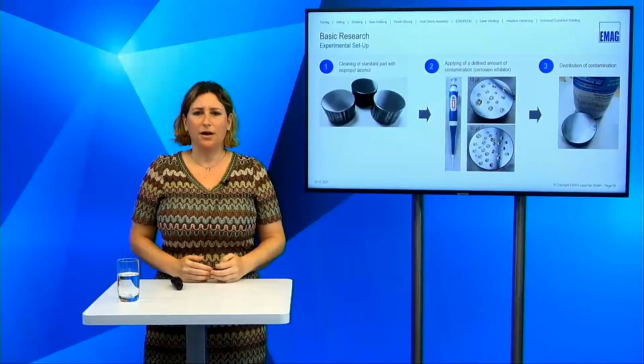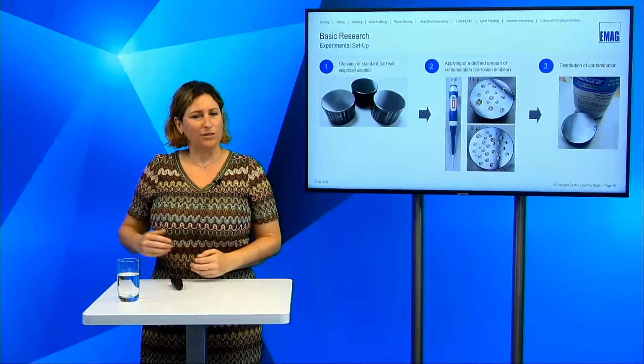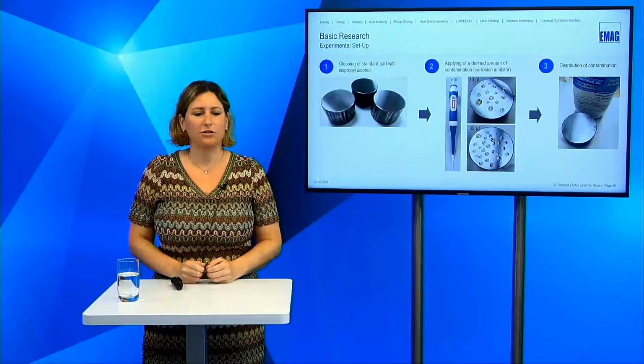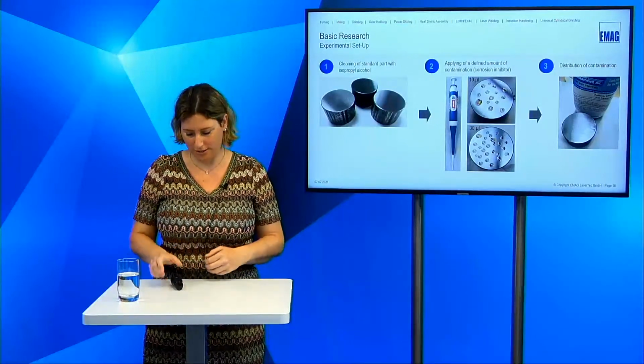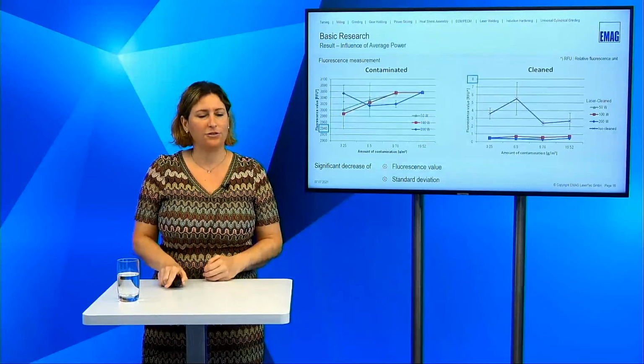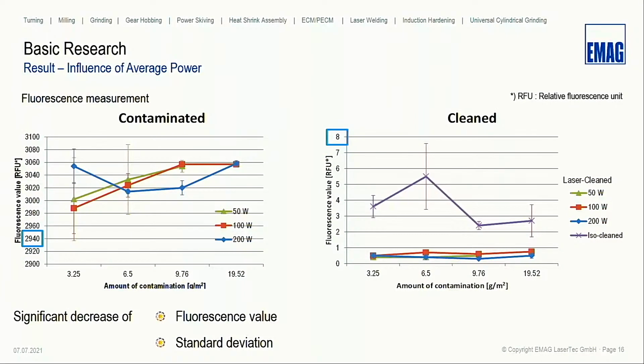How this looks like when you laser clean, and what means clean, and how the surface will be influenced. We did a basic research. We had some samples, put some corrosion inhibitor on it, and we laser cleaned it. And you see, we checked this with fluorescence measurements. For the contaminated ones, you have this high value because you have a lot of liquid on it, which fluoresces a lot. And after the laser cleaning, the fluorescence value is really low, below a value of 1. We compared it also to hand-cleaned surfaces with isopropanol, and this is also a low value, but you can also see this is a low value underneath 6, and the ones for the laser cleaning are underneath 1.